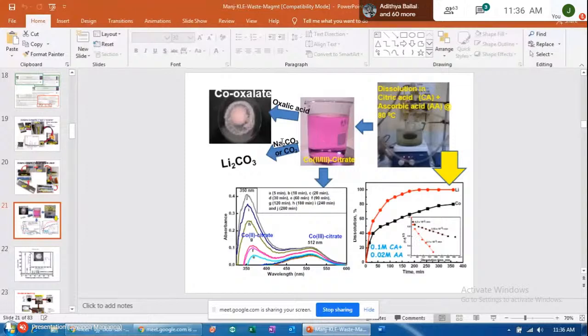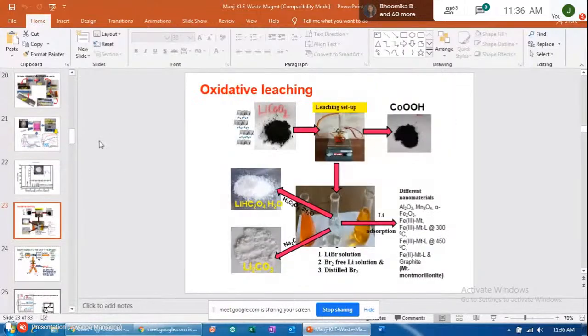Later, I can take cobalt oxalate and lithium carbonate in the stoichiometric amount, grind it, and heat it. They decompose to form a new battery material, so lithium cobalt oxide will be formed. We have done that, and again it is given for reassembling the battery. So our product is back. Now you see, we could save a lot of lithium and also cobalt. Therefore, it's very interesting.